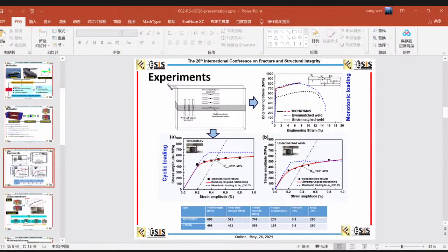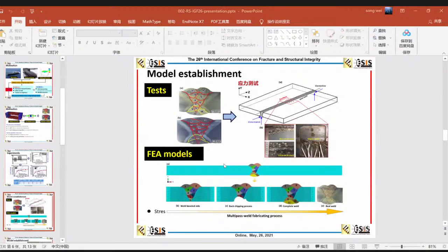So the even matched weldment is the same as the base metal properties. We measured the residual stress of the different welded joints using the deep small hole method. During the FEA processing, we consider the back chipping processing, which is presented on this page.